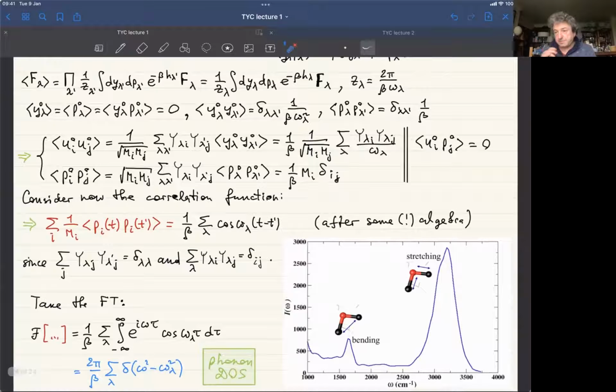Okay, so 3 methods. Frozen-phonon method, which can be used for any system, but requires large unit cells to get access to the K points beyond the gamma point. Density functional perturbation theory, which allows calculating vibrations at any arbitrary K points. But it's heavier than the frozen phonon. Although it depends. If you have to get access to many K points, you have to get very large cells, and then maybe a frozen phonon method becomes more expensive than the perturbation theory.